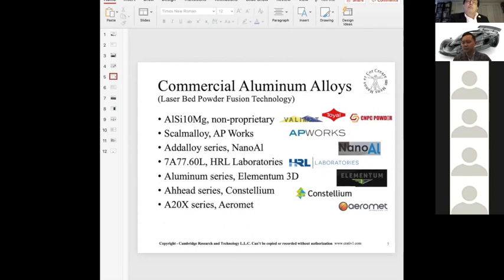Actually, I think there is an ASTM standard now that gives a spec on the amount of oxygen that you can have in titanium. Titanium is the most sensitive to these oxygen phases forming. I think alpha case is a common one, which causes an embrittling effect in your printed material. So that's important to the biomedical industry and the aerospace industry. There are current specs now that recommend the upper limit of how much oxygen you can allow. In terms of aluminum, we also take the same approach. We talk to the manufacturer and we try to reduce the amount of oxygen in the material that we receive. Secondly is in our process parameters,